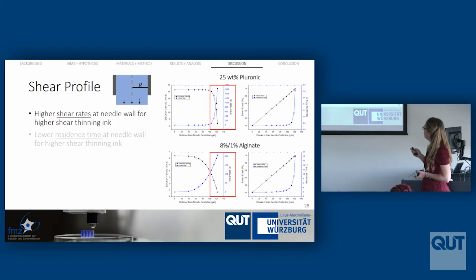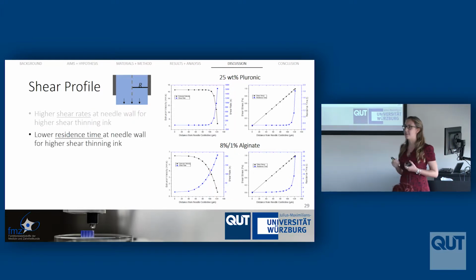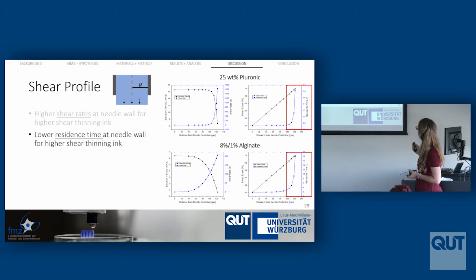For materials that shear thin very highly, so they turn very liquid, we see these very, very high shear rates. But this is quite a different trend for materials that don't shear thin quite as highly. The other one we can look at is the residence time. So let's say I'm a cell and I'm passing through that needle as I'm being extruded. How long do I have to pass through those very high forces that could be damaging the cell and ultimately killing it? And so we can look at the difference for the materials that shear thin.